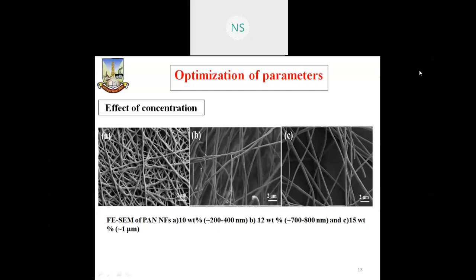And what will be the effect of all these parameters when we optimize them, and what size of fiber will be obtained, that we have seen in the FESEM of the PAN nanofiber. When the concentration of the solution is 10 weight%, the size of the fiber comes in the range of 200 to 400 nanometer. When the concentration is 12 weight%, the size goes too high, 700 to 800 nanometer. And when we go with 15 weight% of the solution, it shows 1 micrometer. Means the concentration of the solution should be minimum. That 10 weight% gives a very precise nanofiber, that is 200 to 400 nanometer size of the fiber can be obtained at 10 weight% concentration of the solution.